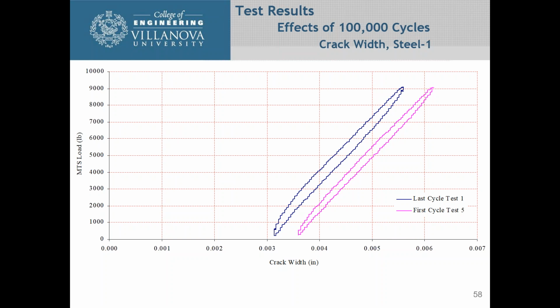So first thing we're going to look at is the steel sample 1, and we're looking at crack width. And you had 100,000 cycles. The black line is the last cycle of the first test of the service, and the magenta line is the first cycle of test 5, which was the first one of the 10 cycles of service after we ran the 100,000. And you can see that the slopes are pretty much the same.